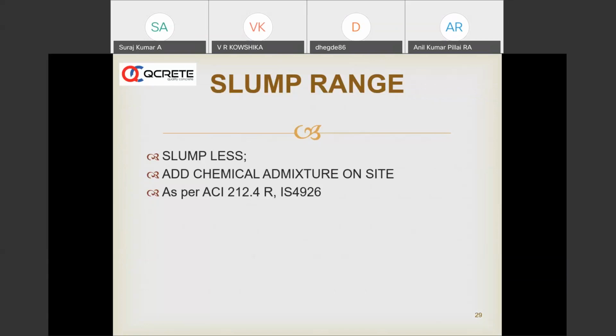What do you do if the slump is less? If the slump is less, as per ACI 212.4R, and even as discussed in IS 4926, you can have a small addition of admixture on site by trained technicians. Generally we add about 0.1 to 0.2 or 0.3% maximum by weight of cement or cementitious system.